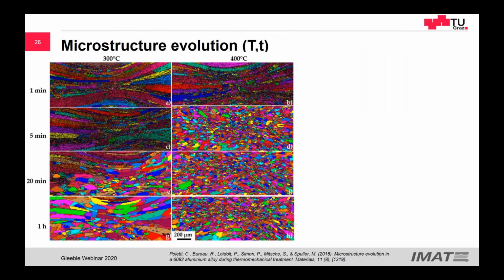So very nice pictures delivered by the EBSD, of course, and here you can see with the temperature and different holding times what happens. This is not in situ, there are different samples. And after treatments, you can see the very first recrystallized grains, very small, and here as well. So this green is a recrystallized grain. You can see the larger the temperature, the smaller the grains are in this case. And this is because we have a lot of nuclei. The nucleation rate is dependent on temperature. So the higher the temperature, the faster the nucleation rate. And then the growth rate is usually much slower. So we just end up with a bunch of very fine grains.